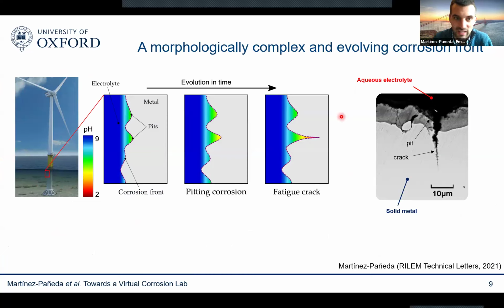But anyway, what you see here is a typical example. You have a metallic structure exposed to an aggressive environment, in this case, seawater. And as you can see, first you generate those pits. Then those pits start evolving in time, and eventually you get the pit to crack transition and the propagation of these corrosion fatigue cracks. And again, it is a very strongly coupled problem, where we need to capture this morphology very well, because how this morphology evolves, how those pits grow, is dependent on the local chemistry and mechanics, but at the same time, the local chemistry and mechanics themselves are dependent on the shape of those pits, right? So if you have a sharper pit, of course, you're going to have higher stresses and lower pH and so on and so forth. So everything is very strongly coupled.